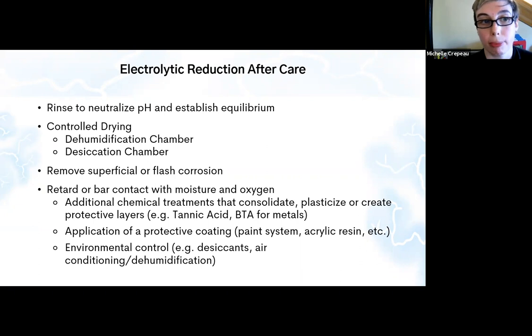After the rinsing process, we then go through a period of controlled drying, which for metals can take place in a desiccation chamber or other type of dehumidification chamber where we can slowly reduce the atmospheric moisture and very precisely dry the artifact so that it doesn't dry too fast and then we experience damage or continued corrosion. Often in the rinsing phase, you will have some type of superficial or flash corrosion that forms on your artifact, so that will often need to be removed.